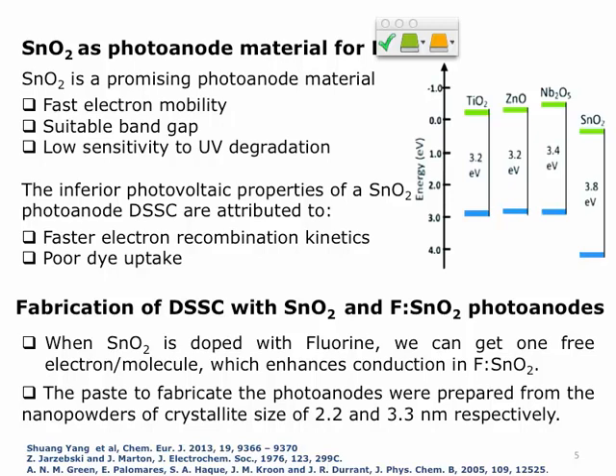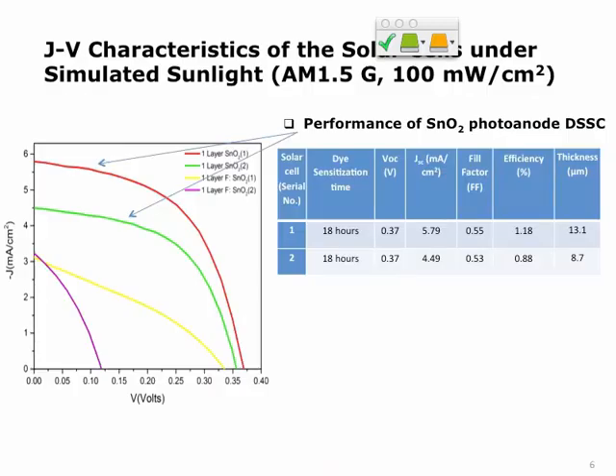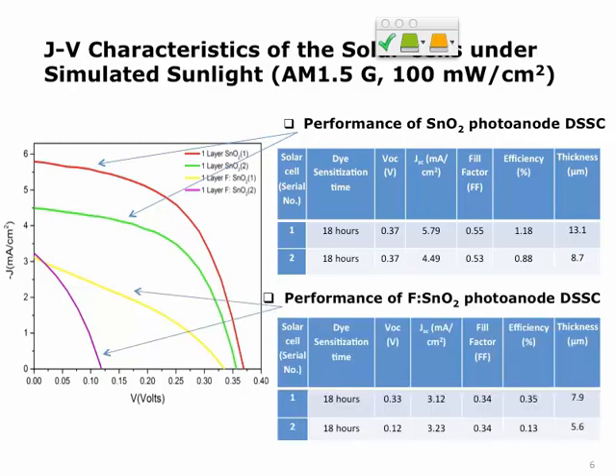There is also motivation for using smaller size particles because a smaller size gives a higher surface-to-volume ratio, allowing more dye absorption. We prepared the photoanodes and tested the solar cells for both tin oxide and fluorine-doped tin oxide. The performance is around 1% for tin oxide, and the fluorine-doped tin oxide, which we expected to perform better, actually shows lower performance. This is partly because the paste is not perfectly homogeneous, causing variation in film thickness.